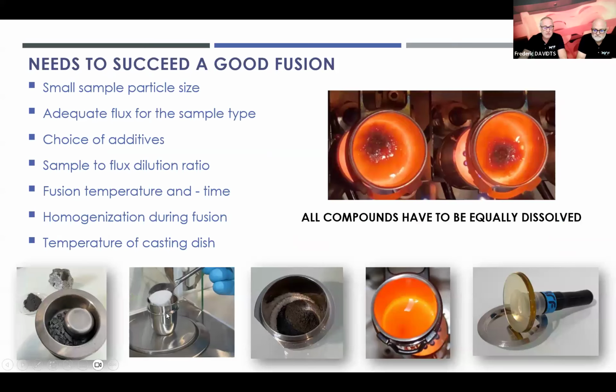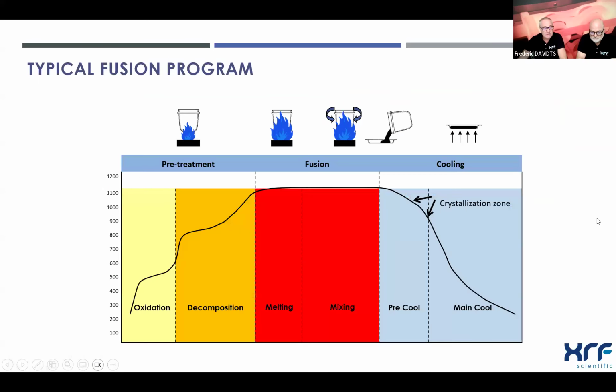There is a number of tools that we can use to make our life a bit easier. More details will follow later on, but in order to have a good fusion it is important to have a small sample particle size, an adequate flux for the type of sample that we analyze, additives to choose from, the right sample to flux dilution ratio, appropriate fusion temperature and time, that we homogenize the sample during the fusion, and also that our casting disc has an appropriate temperature to cast the content of the platinum crucible. More details will follow in the second part of the presentation.